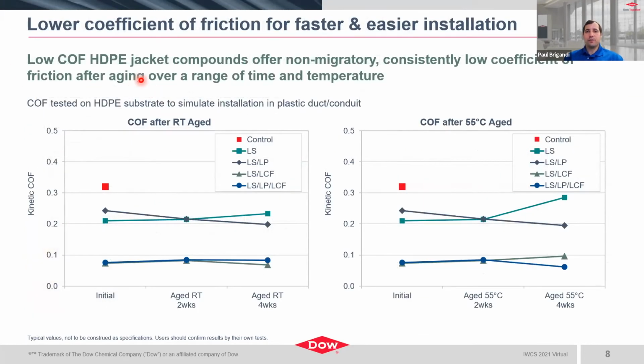Now we'll look at the coefficient of friction, again, for faster and easier installation. So these compounds, typically your high density polyethylenes, are going to have the lowest coefficient of friction amongst the polyethylene type jacketing materials, even so, probably lower than many of the other materials used as well. But again, in the polyethylene family, HDPE is going to have the lowest. And so here we're actually looking at further improvements over the HDPE itself, and actually looking at it over a wide range of temperatures and different aging times. And so there's two key points that we see from this data.